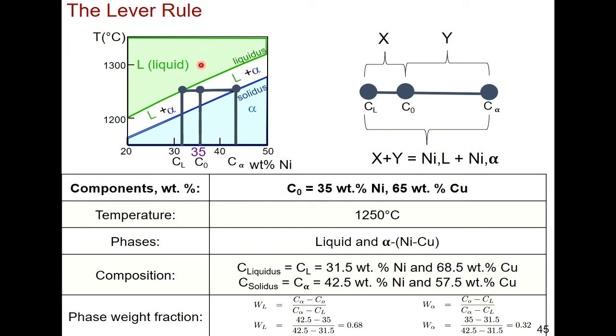You're still in liquid in the green region, and then you hit the liquidus line. Some of your material is going to start solidifying, and then you're going to get some alpha, but the majority of your material is still in liquid form, right? It's still in the liquid phase, and you drop the temperature down some more, and if you happen to be at 1250 C, you can quantify how much liquid you have and what is the weight fraction of solid that you have, right? So you can track the amount that has solidified just based on the phase diagram.